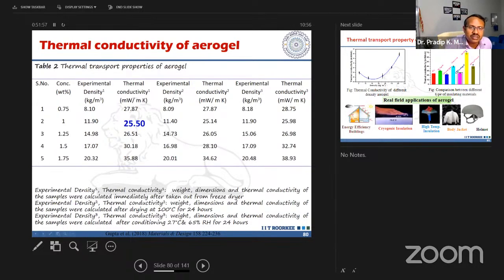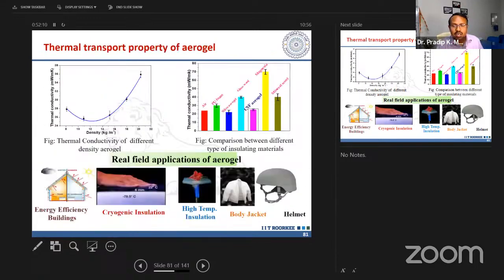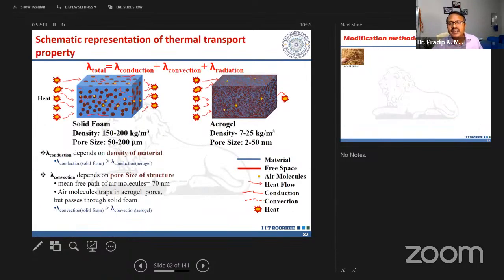For the 1 weight percent cellulose nanofiber aerogel, we are getting 25.50 milliwatt per meter Kelvin thermal conductivity. Now I'm trying to explain why this is happening. If it is in the mesoporous range, what is the pore size? As I told you, the pore size is somewhere in the mesoporous range, 2 to 50 nanometer. If you have the idea, the mean free path of air is somewhere around 67 nanometer. For thermal conductivity, at least the mean free path of air is really required to transfer the heat from one part to another part.